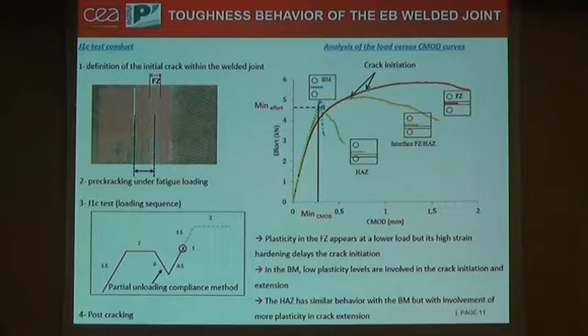On the other hand, the base metal is hard, but the crack initiation and growth... finally we have a low level of plasticity involved in both crack initiation and growth. And the heat affected zone has a similar behavior to the base metal, but with the involvement of more levels of plasticity for crack extension. And this denotes, one more time, the high undermatch in toughness as well as in tensile behavior.